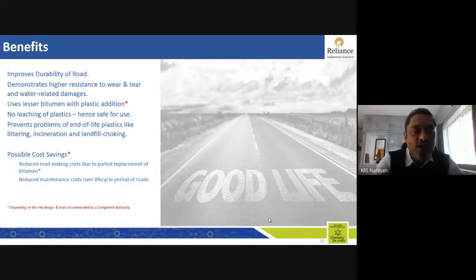So we did this to ensure that we have a practical feel about the performance of the road after a year or two. What has happened is, we managed to ensure that the plastics actually have a solution. The end-of-life plastics got a solution, and because our township was generating a lot of these multi-layered plastics, we found great use for it. And then we used it for the durability of the road itself. So we had a partial replacement.